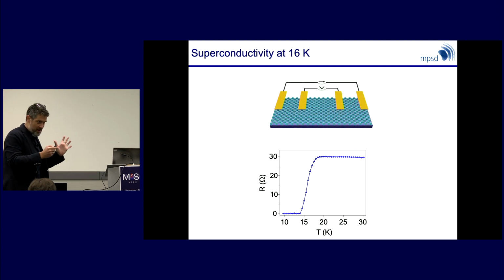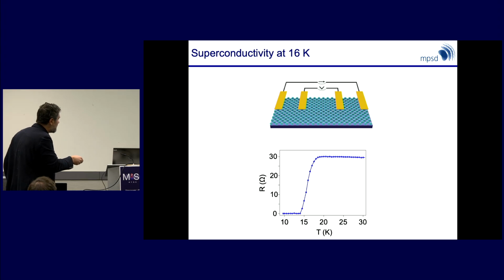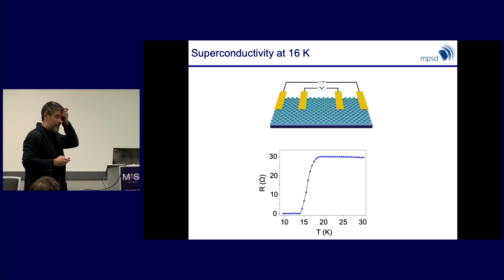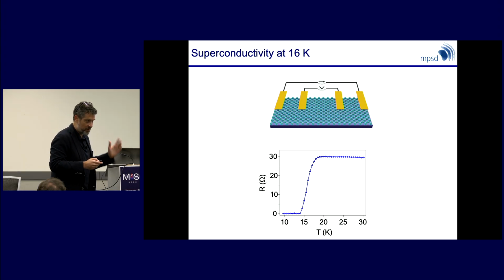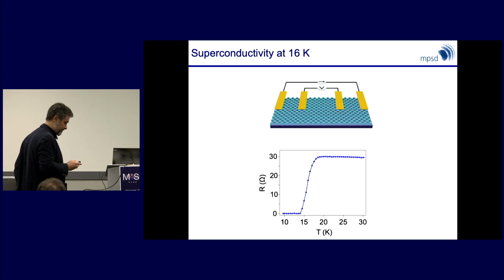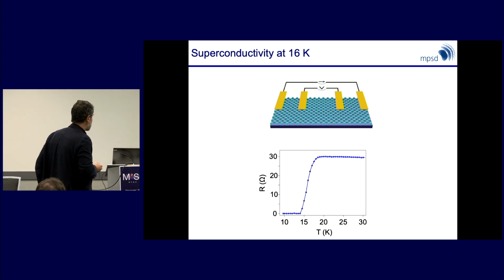It's kind of hard, but if you do it long enough, you find really nice thin films. The transition is a little bit broad, but the transition temperature is 16 Kelvin, where it's supposed to be. These are different samples than the ones we used for the other experiments, but they are superconducting at the right place, and the densities are right. The Hall effect is what it's supposed to be, so they cannot be completely different from the powders.